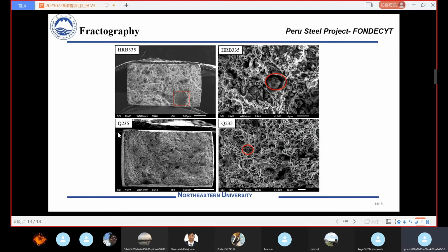Then after we get some parameters to evaluate the mechanical properties, we can also observe the fracture surface. These are the fractographs taken from the fracture surface. We can find some dimples. There are many dimples and quasi-cleavage, and if we observe in more detail, we can find that at the bottom of the dimples, there are many large particles.